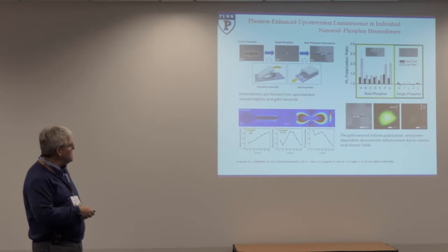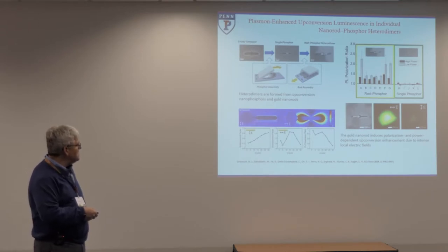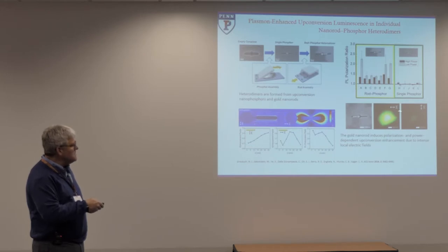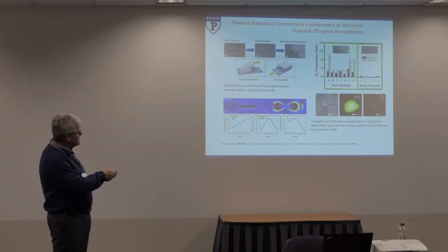So there are a couple things that come from these kinds of experiments. It allows you to build a series of structures that have controlled arrangements of the emitter and the antenna. And then because you know where they are, you've actually indexed the positions, you can then do the optical spectroscopy and the electron microscopy on the same spot. And that's important because then you get to measure all those distances that we said were really important, in terms of not just the average distance between the emitter and the structure, but what happens when one of the pieces is out of place. Maybe this guy actually is slightly closer in to this side than it is to the other side.